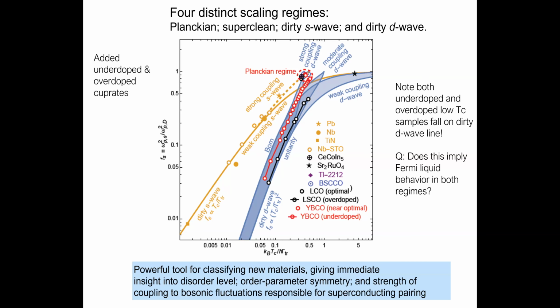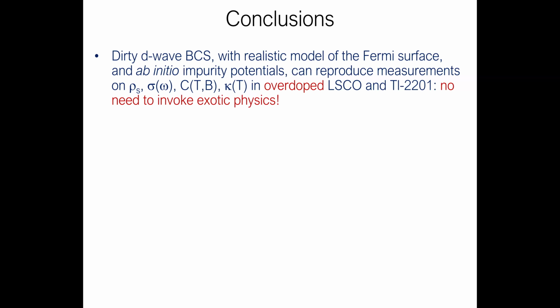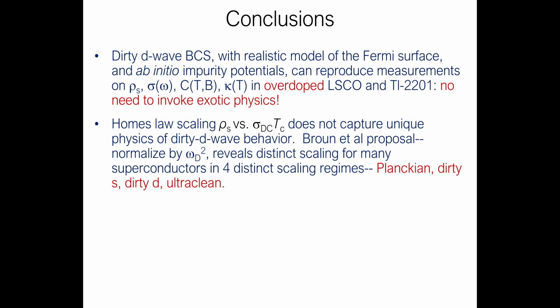Okay, so the message here is that this is now a tool for classifying materials that gives immediate insight. This way of plotting things gives immediate insight into the disorder level, the order parameter symmetry, and the strength of coupling to bosonic fluctuations that are responsible for the superconducting pairing. So, the messages in the conclusions now. Dirty D wave works pretty well to explain these bulk properties. The Homes scaling, the new thing I showed you, does not capture the unique physics of dirty D wave behavior. So we have this proposal of normalizing by the Drude weight, and then you see that there are four distinct scaling regimes: Planckian, dirty S, dirty D, and ultra clean.